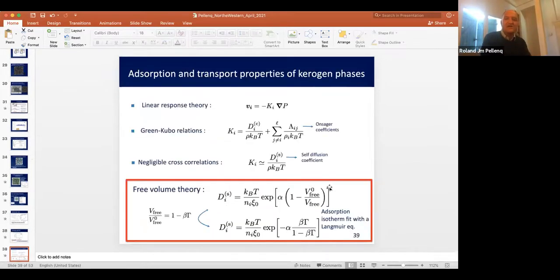Okay, fine. So let's move to what we can do then. We can go back to a very fundamental equation. We start from the linear response theory, where the velocity or the flux is proportional to the gradient. And now we're not splitting this constant that we call the permeance into the viscosity and permeability. We just stick to one coefficient that we call permeance, and that we can show from physics is related to the transport coefficient Dc of species i, and also the cross coefficient between the two species, which are called the Onsager coefficients.